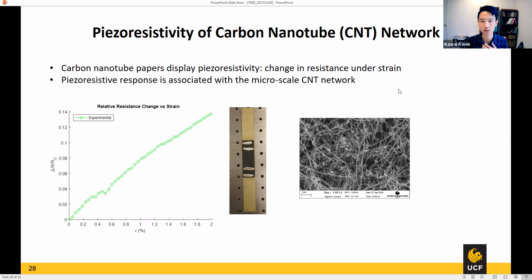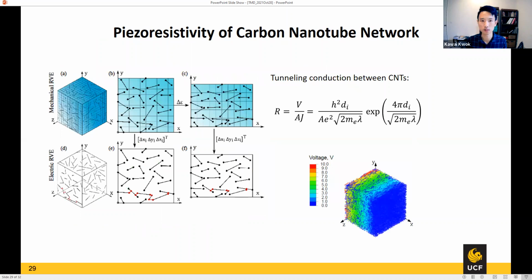But there are a few things about this strain sensing, the sensitivity or the strain gauge factor of that carbon nanopaper. That is because sometimes they're not very repeatable, depending on how the carbon nanotube paper is made. Fundamentally, it's really a network of carbon nanotubes. It's a mesh, and so there's a lot of microstructure effects going on there. So what we did is, we go in and try to understand it, so that maybe we can control the microstructure and have a more consistent gauge factor.